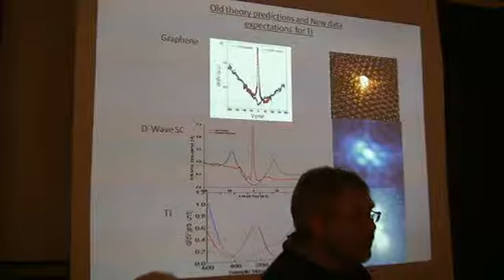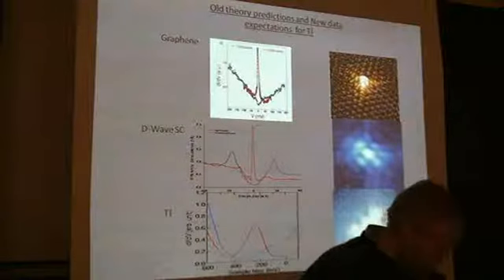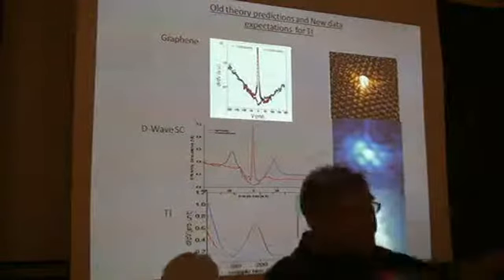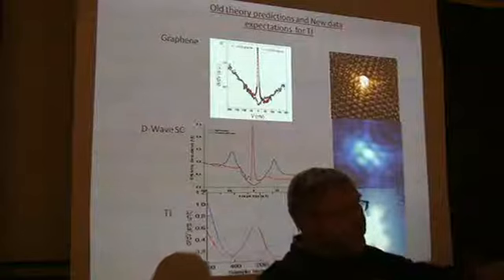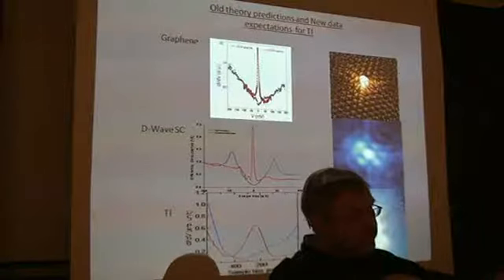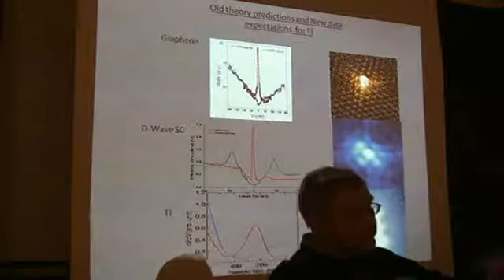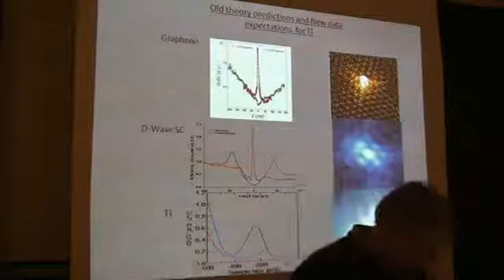If you look at the ARPES, well, we can show it at the end. Basically, you can see that there are contributions from the other states, and maybe right in the middle vicinity it's symmetric, but the rest has quite a bit more states on the filled side than on the empty side, even in ARPES.